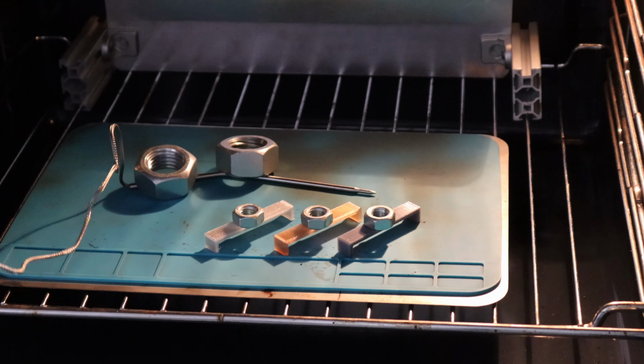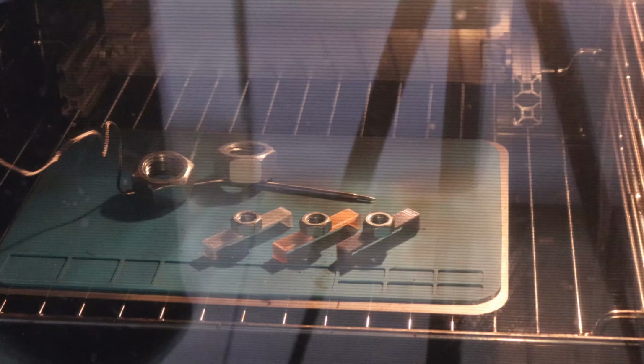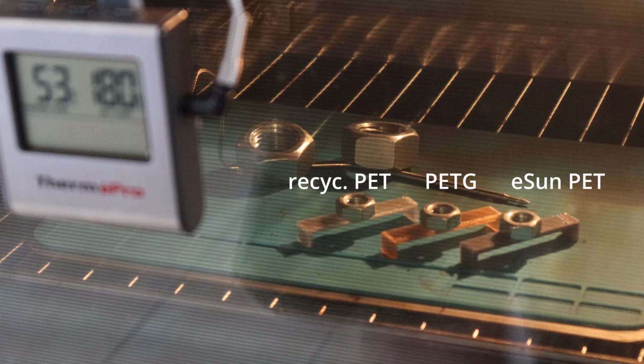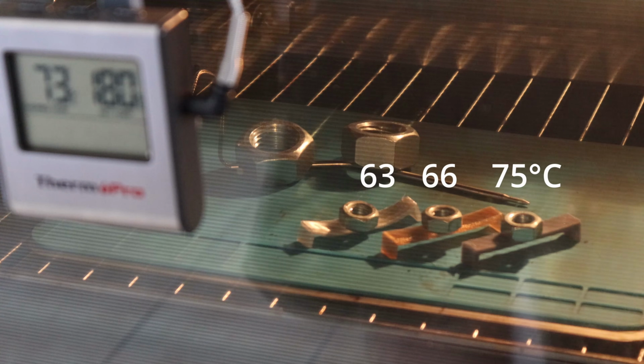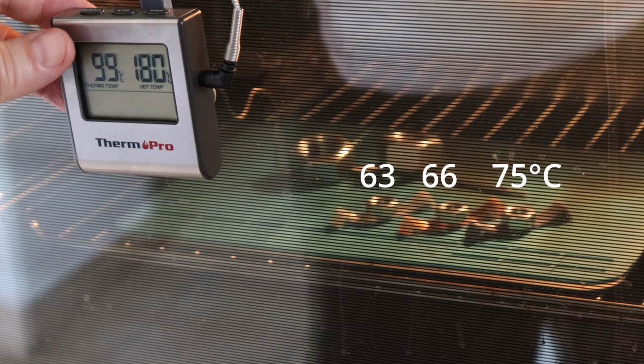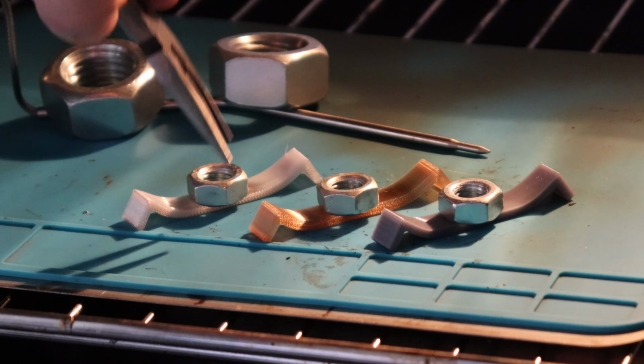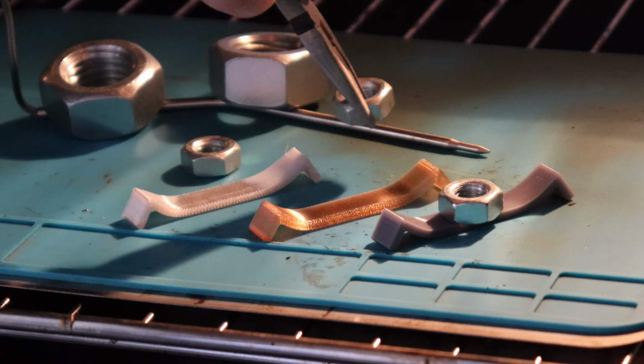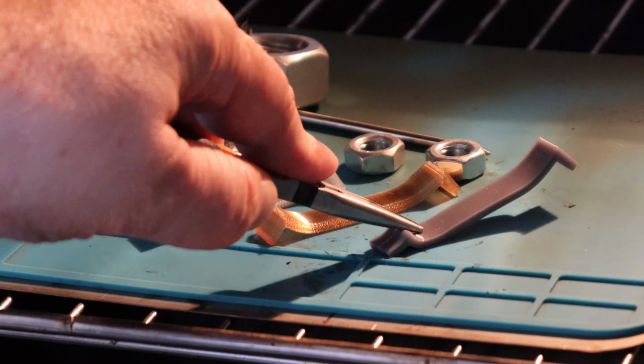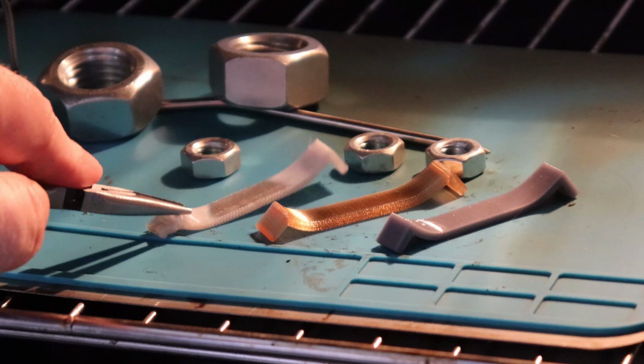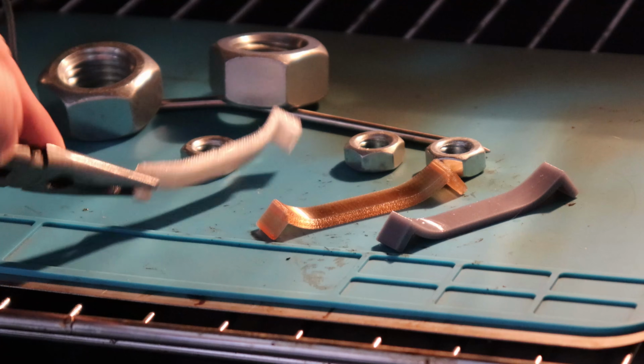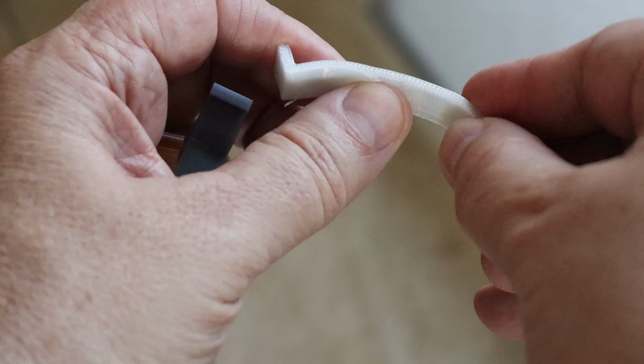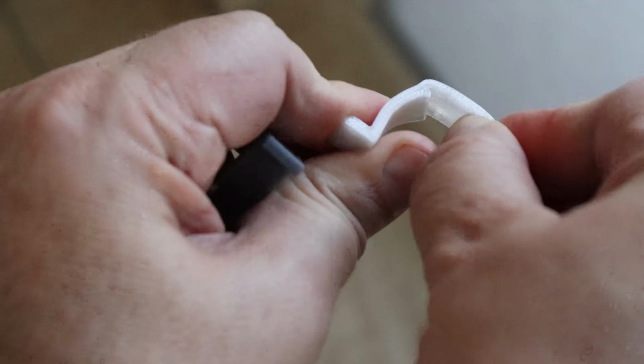Temperature test in the oven. I want to record the temperature of the first deformation, and PET started to deform quite early, like PETG, and the eSun PET was the best in this case. With the PET, annealing could help with the temperature resistance, and at this point they are very similar to each other. But again, a reminder, this transparent PET was printed with big underextrusion.